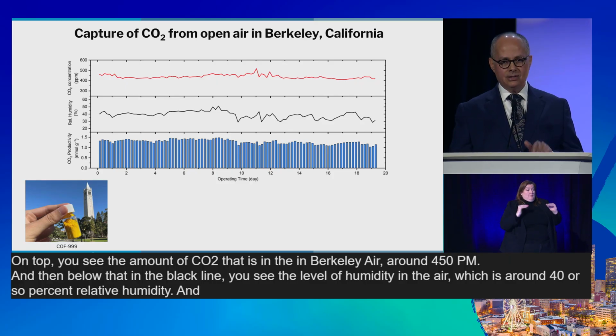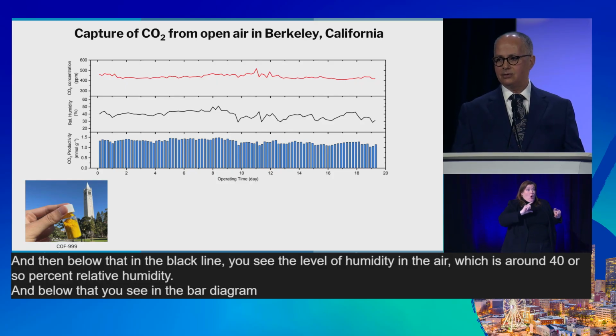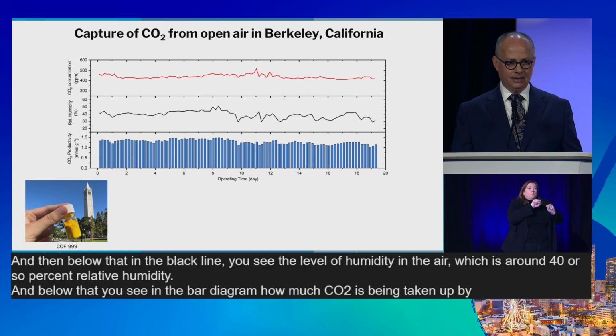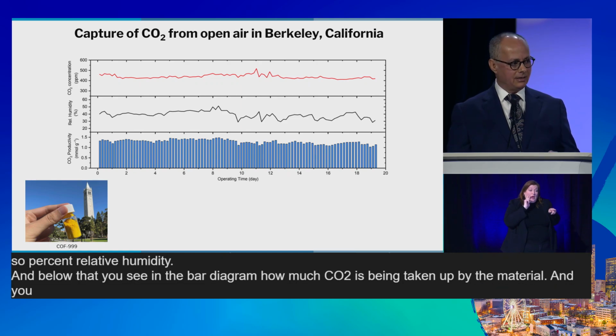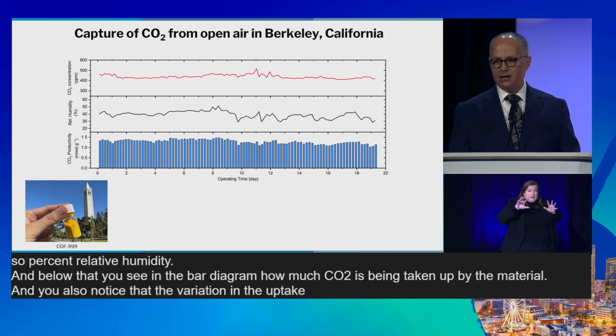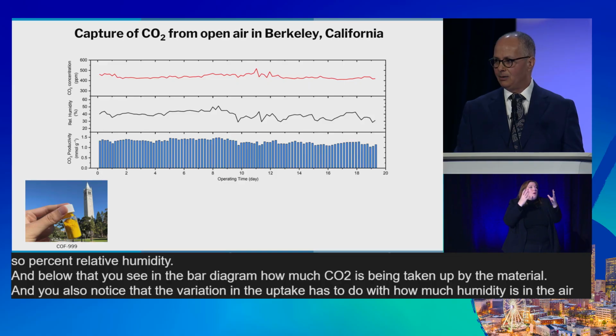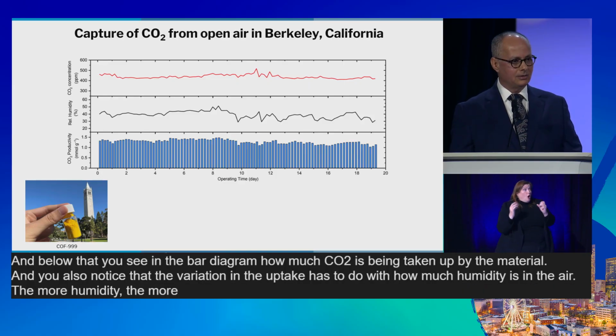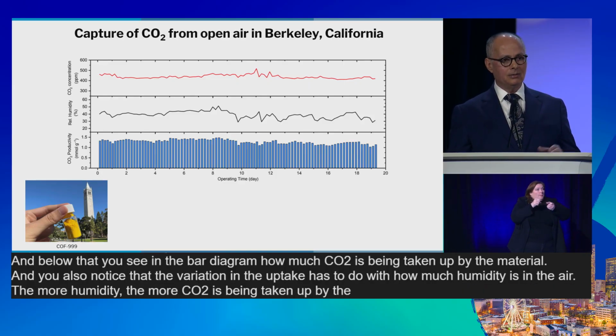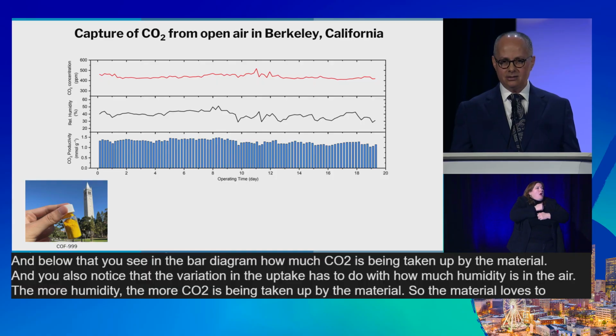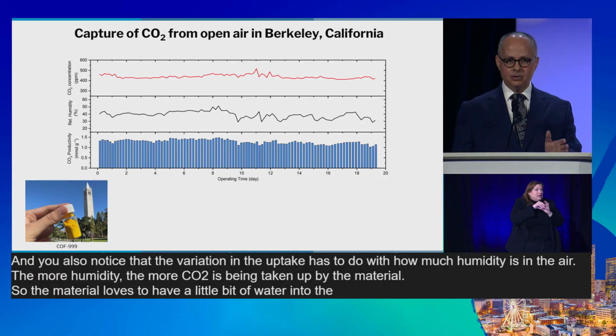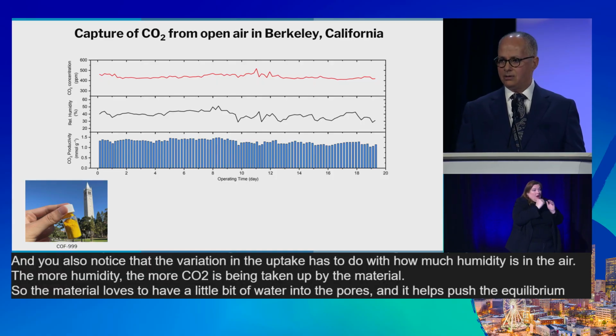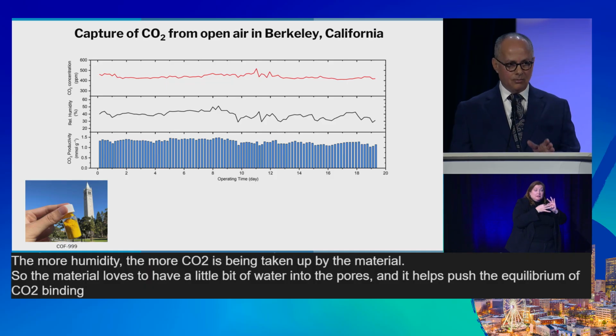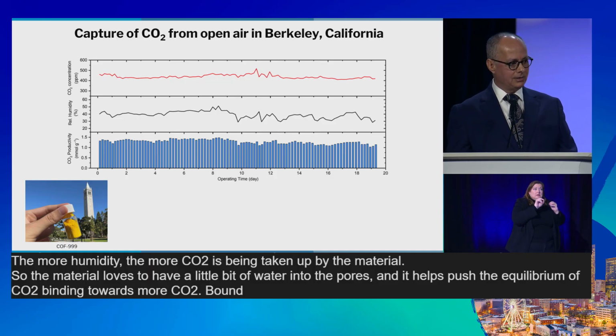And below that, you see in the bar diagram how much CO2 is being taken up by the material. And you also notice that the variation in the uptake has to do with how much humidity is in the air. The more humidity, the more CO2 is being taken up by the material. So the material loves to have a little bit of water in the pores, and it helps push the equilibrium of CO2 binding towards more CO2-bound species.